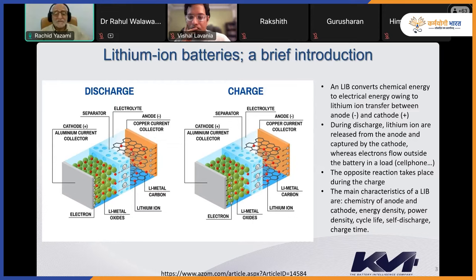And the electrolyte usually is stored in a microporous polymer separator that mechanically separates the anode and the cathode. Then the lithium ions diffuse in the electrolyte and go to the anode, which is graphite. Lithium is intercalated between the graphite, or graphene, layers. So the graphite is the anode, which is the minus pole of the battery.